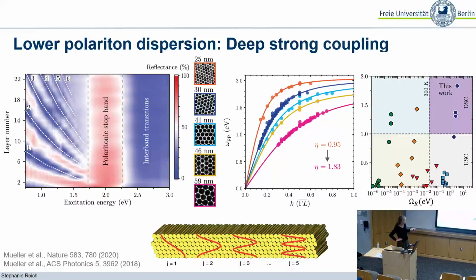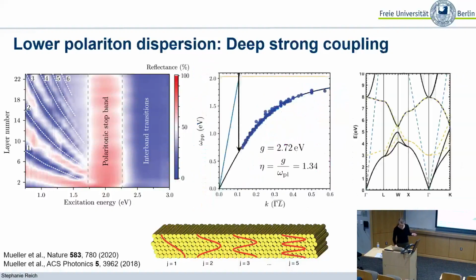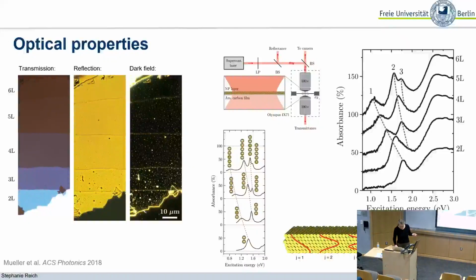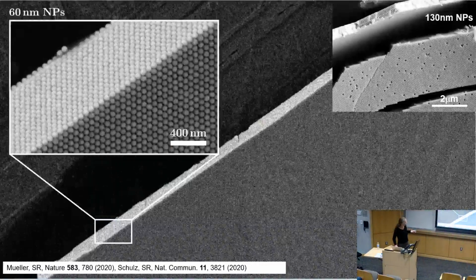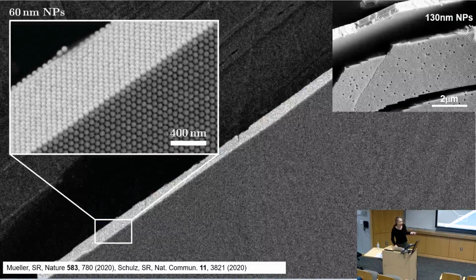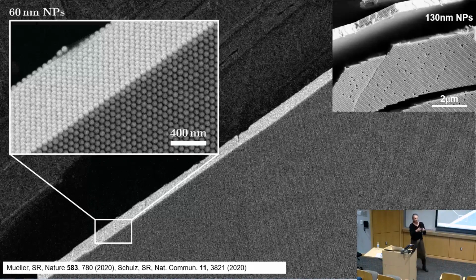But there's also a very nice paper where Florian discusses these things. So here's this Nature Communications paper. There he looks at how the length of the ligand affects the distance between the gold nanoparticles and so on. Naively, as a physicist, I would think that if you make it longer, the gap is larger, and you could really scale it with the length of the polymers. That only works for a certain size of the gold nanoparticles and then doesn't work very well anymore.